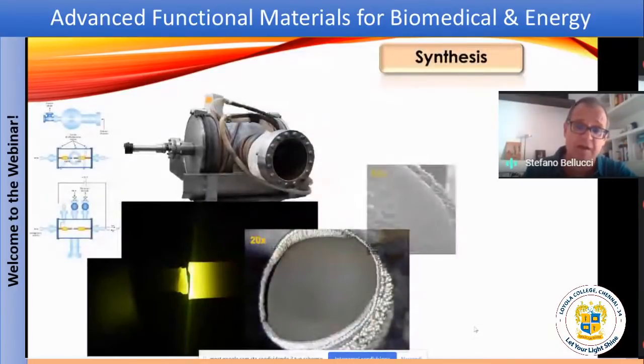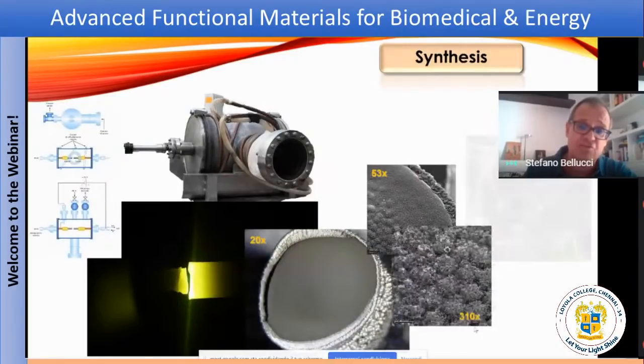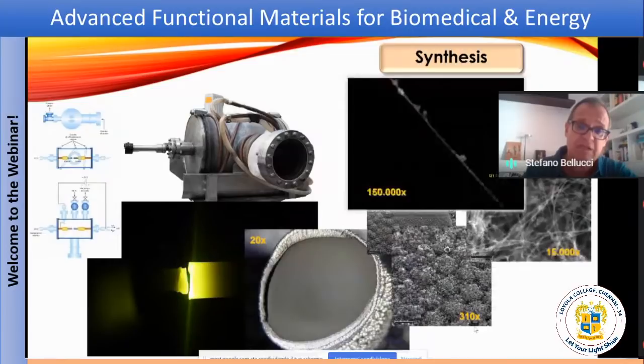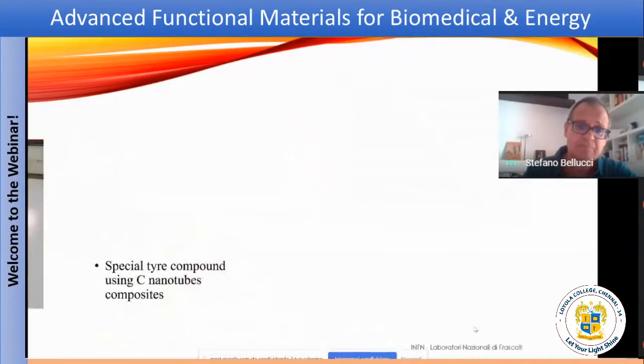So here you see an example of our early production by physical method of very, very pure carbon nanotubes. Here I show you also different magnification, and you can see that these nanotubes are mechanically very strong. This is a multi-wall nanotube, 20 nanometers in diameter, and it's obtained by arc discharge.